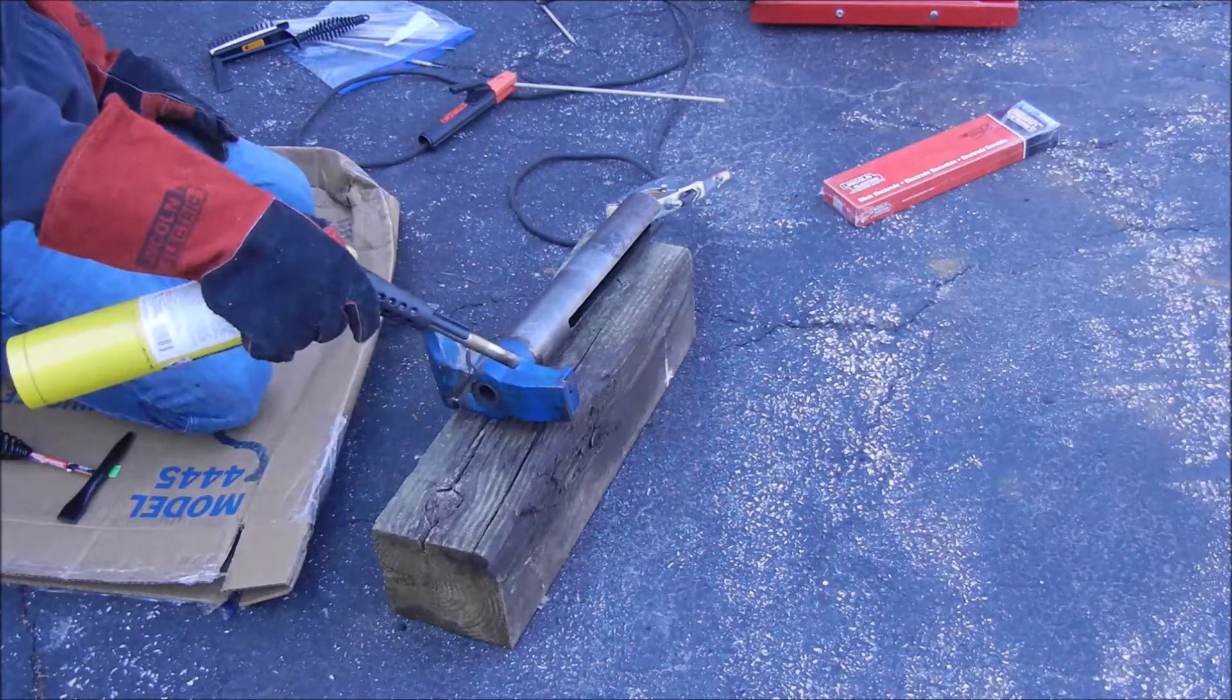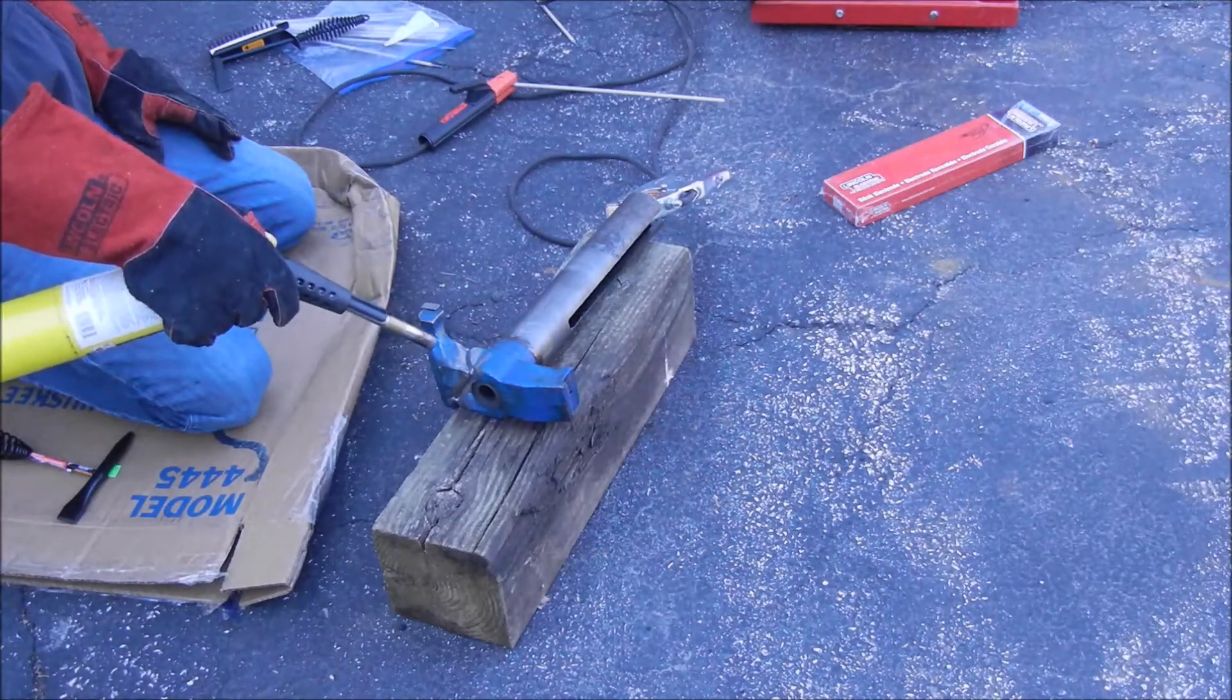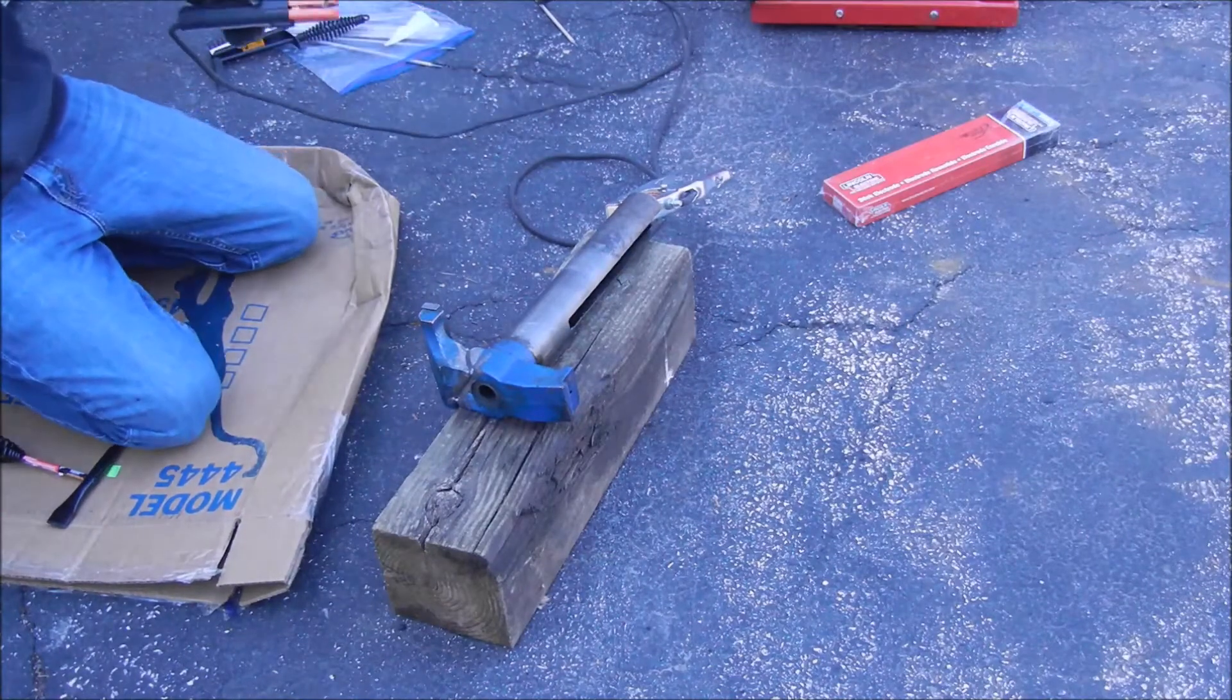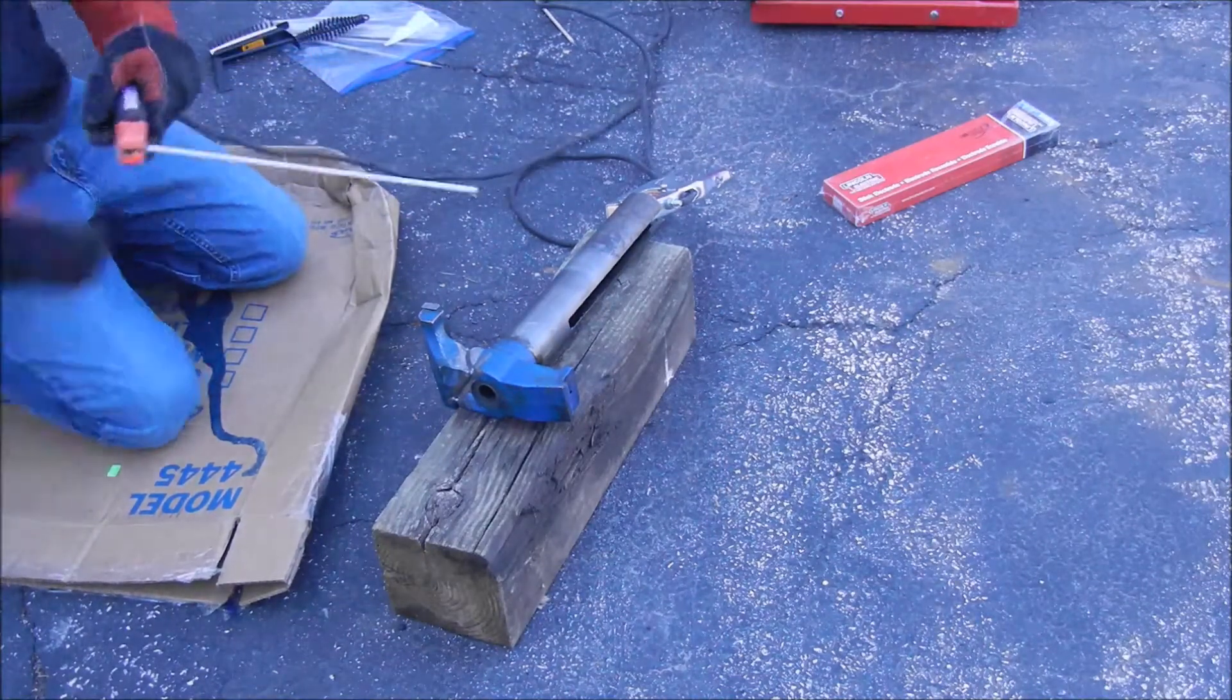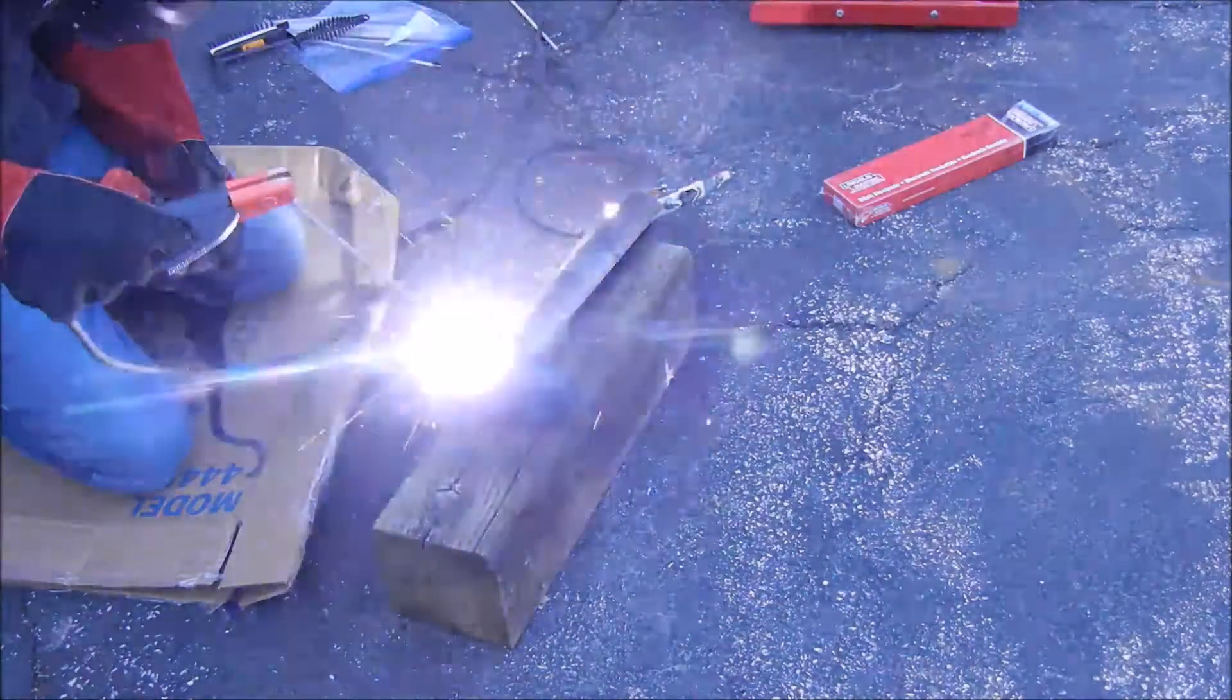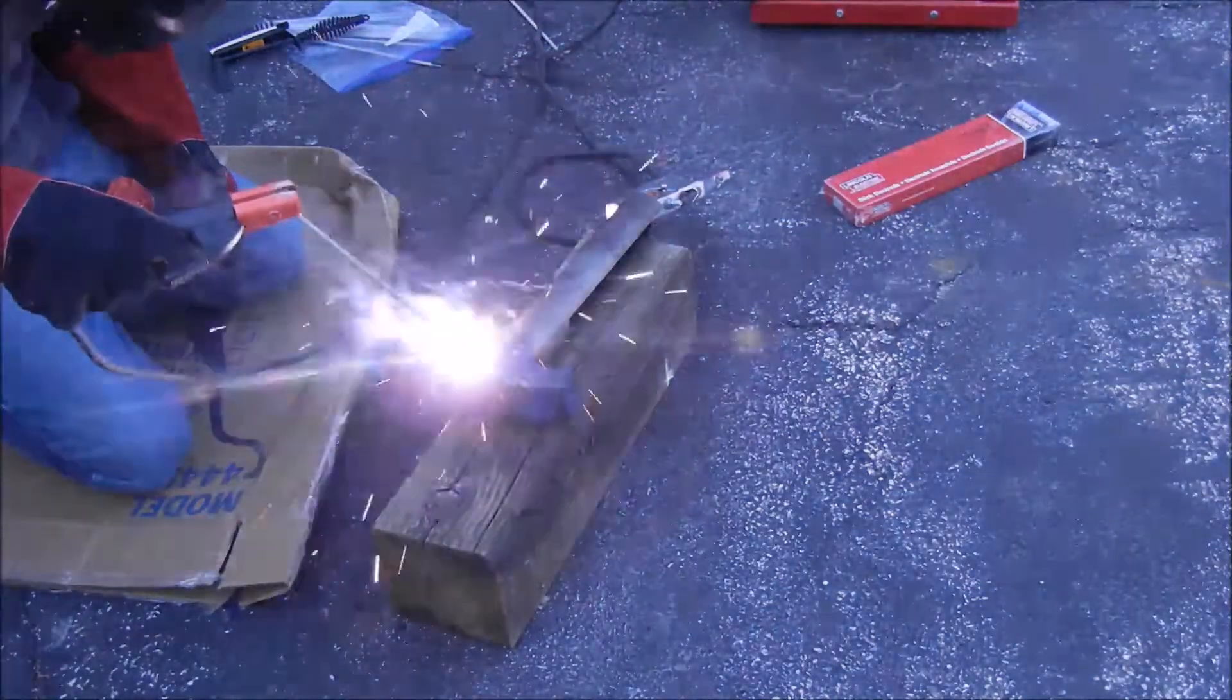I'm using a Lincoln AC-225 stick welder with a 7018 rod. I beveled all my joints and preheated the material as evenly as possible with a blowtorch.